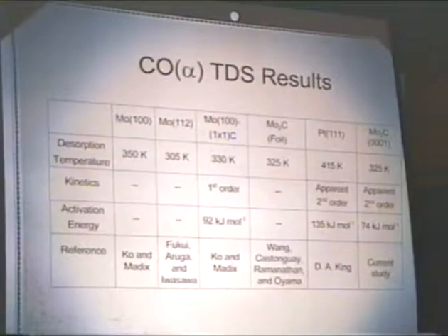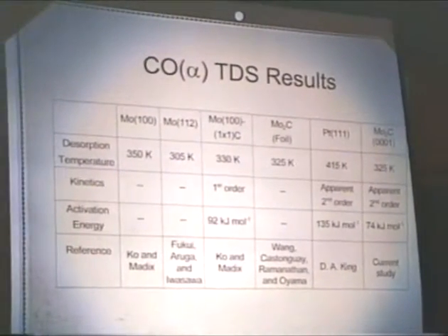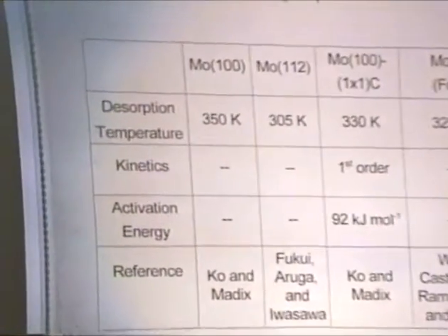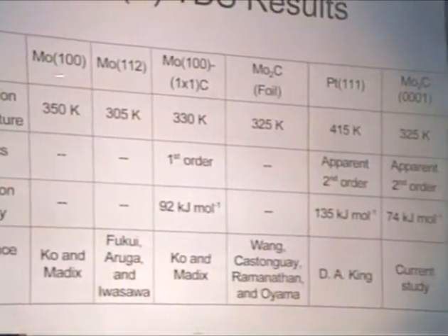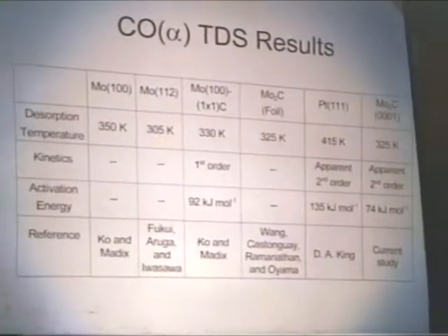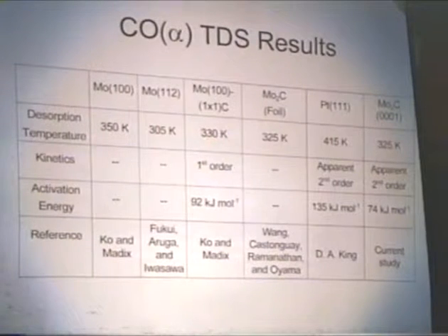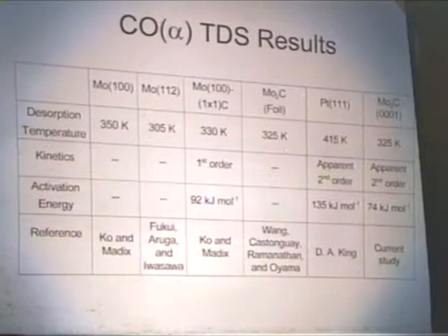To start wrapping up the results, this is a comparison of the CO alpha phase, the molecularly adsorbed CO desorption, from a number of different systems. From two different Mo single crystal systems, we see a desorption temperature between 305 and 350 Kelvin. While across three different carbide systems, whether that be a carbon overlayer, a molycarbide foil, or the current study using a single crystal molycarbide, we get a consistent desorption temperature between 325 and 330 Kelvin.